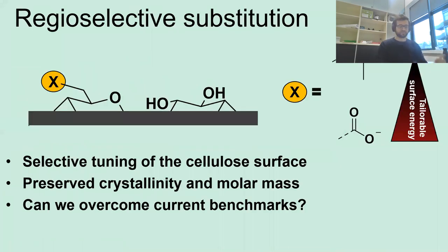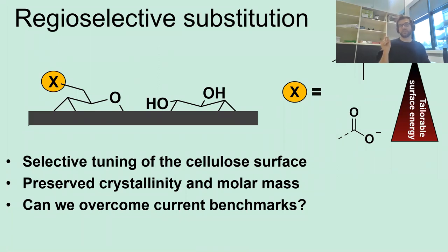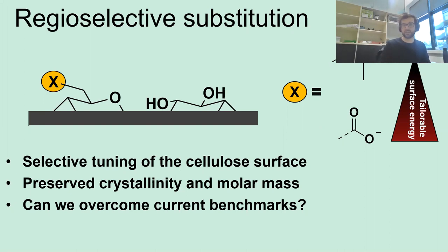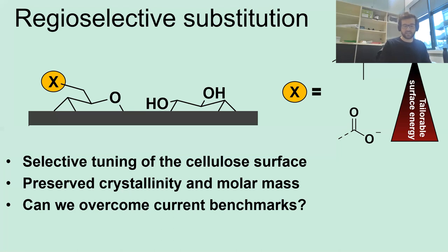In the latest work, we also managed to establish a protocol for regioselective esterification, whereby we can selectively introduce chemical functionalities on the primary hydroxyl groups. This is conceptually similar to TEMPO oxidation, but we can introduce any functional groups we can think of, thereby tailoring surface energy. In contrast to periodate and TEMPO oxidation, we can really preserve crystallinity and molar mass. We believe this can overcome current benchmarks in mechanical performance, and we hope to share more about this at the next meeting.